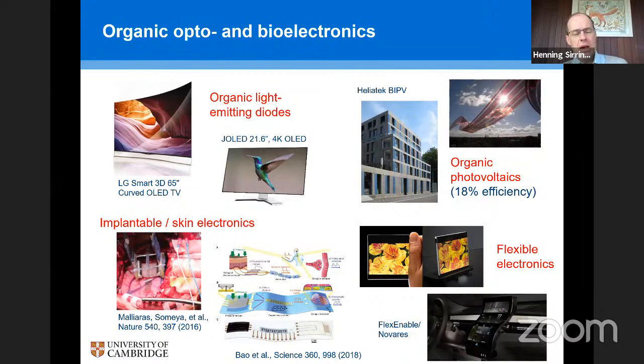You're probably familiar with organic light emitting diodes, where lots of TV displays and mobile phone displays use organic semiconductors as the light emitting diode elements on the different pixels of the display. There is a whole effort to realize organic solar cells, organic photovoltaics. That's not quite as mature commercially as the organic LED displays, but the efficiency of organic solar cells has also improved greatly. It's now about 18% power conversion efficiency. That's still a little bit lower than silicon, which is around 20–25%, but it's certainly an interesting future application for these materials.